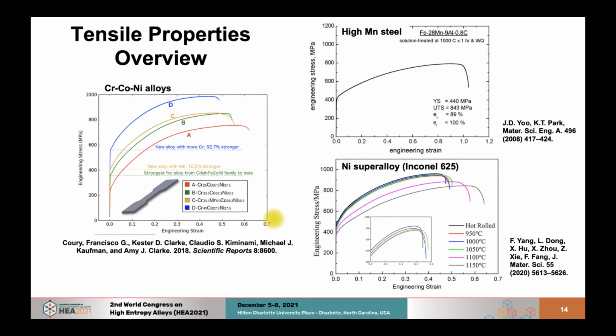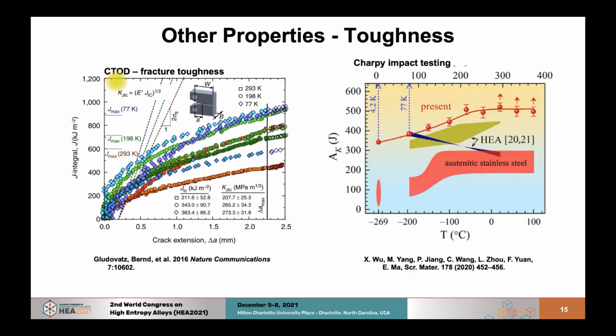And the reason we say that is because if we compare the tensile stress-strain curve of these alloys with, for example, some austenitic high manganese steels or some austenitic or gamma nickel superalloys such as Inconel 625, we see that these alloys are good, but would hardly justify the high cost, especially due to the high cobalt contents. So we really need to look beyond tensile properties alone to justify their application.